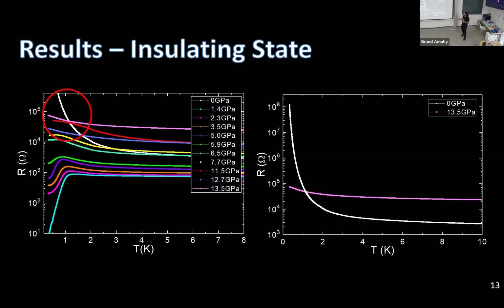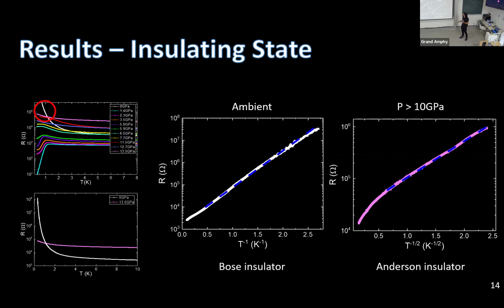At ambient pressure, we can see that when we cool down our sample, we have an order of magnitude higher resistance. So trying to fit those two different insulating states, we see that at ambient pressure we have the Bose insulator, which we saw again and again at ambient pressure on disordered indium oxide samples. We have activation behavior, R goes as T to the power of minus 1, but as we pressurize our sample, we undergo another transition from Bose insulator to another insulator, where we see a normal fermionic insulating behavior under higher pressure.